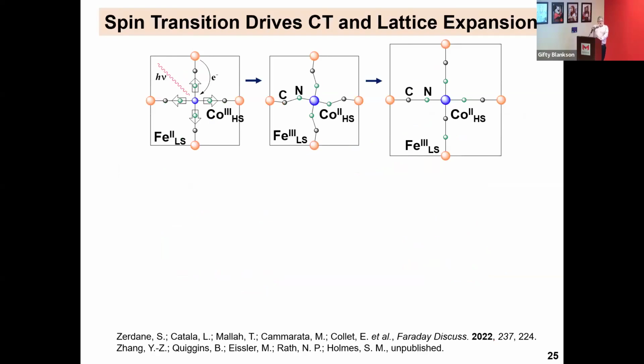So in cartoon land, you shine light, get electron transfer from the iron to the cobalt. You haven't given enough time or energy to relax, so you have a stable structure. That's why you have these bent cyanide bridges. And then with enough time, it expands the lattice, allows that electron transfer to complete its task to that vibrational state, which you can actually measure, and people have done that now.